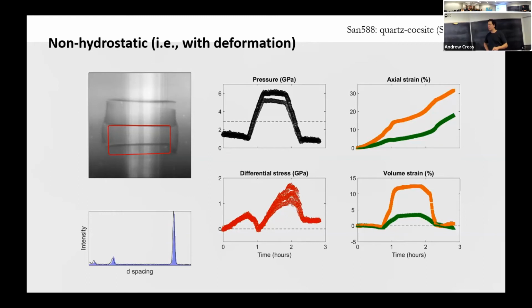But then in this case, the axial strain increases throughout the experiment just because we're pushing on the sample, we're deforming it. You get a tick up in the axial strain, so it shortens as it goes through the phase transformation as the volume is decreasing. But then on the way back down, the volume's increasing. So you might expect the sample to lengthen, but instead it shortens again.